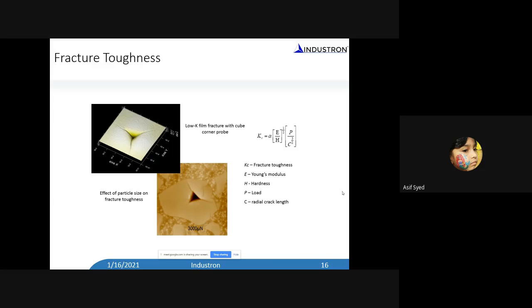Again, because we have the imaging capability, you can do an indent on a ceramic material. When you do an indent on a ceramic material with what we call a corner cube indenter tip, which has a higher strain, you generate a crack, and you can measure this crack length through the image. And you know the Young's modulus and the hardness from the same indentation experiment. With all these parameters, you can even calculate the fracture toughness. It's not as quantitative as your regular fracture toughness measurement, but for ceramic material, if the crack length is much longer than the width of the indent, it does work. So in that process, you can calculate the fracture toughness of this material.